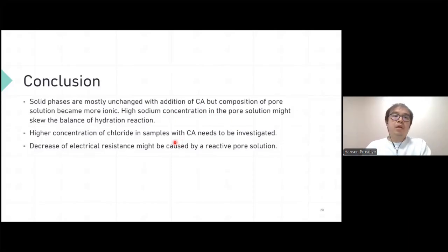So to conclude, the solid phases are mostly unchanged with addition of CA, but the composition of the pore solution became a lot more ionic. I think that's a cause for concern, because we can see that electrical resistivity went down in samples with CA. Also, the high sodium concentration in the pore solution might skew the balance of other hydration reactions. The higher chloride in samples with CA needs to be investigated.